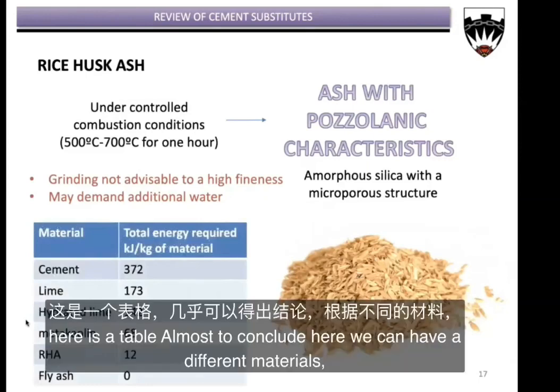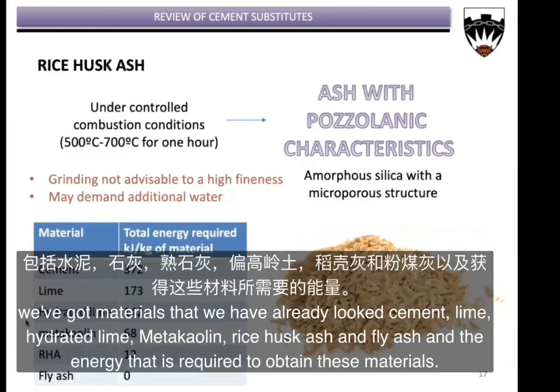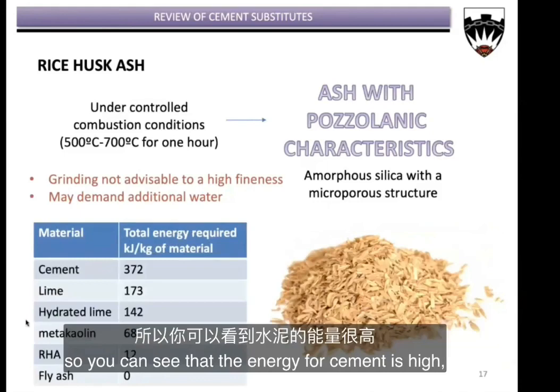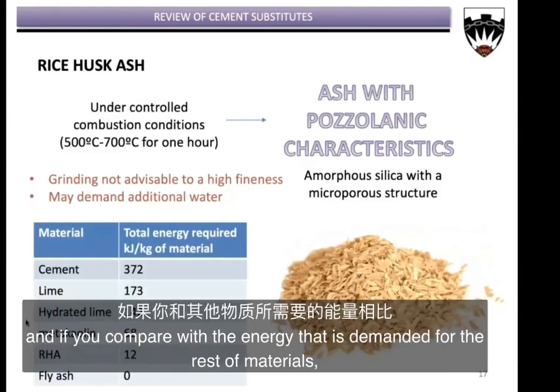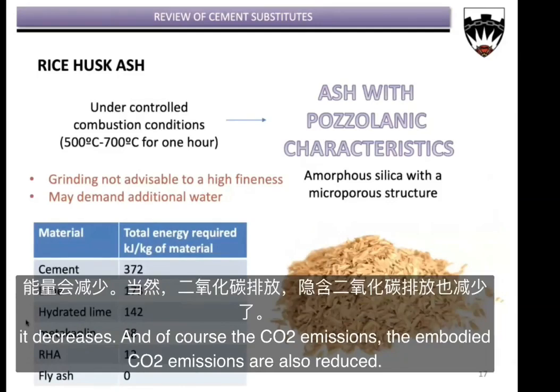Well, here is a table, and it is almost to conclude. Here we can have different materials. We've got materials that we have already talked about: cement, lime, hydrated lime, metakaolin, rice husk ash, and fly ash, and the energy that is required to obtain these materials. So you can see that the energy for cement is high, and if you compare with the energy that is demanded for the rest of the materials, it decreases, right? And of course, the embodied CO2 emissions are also reduced.